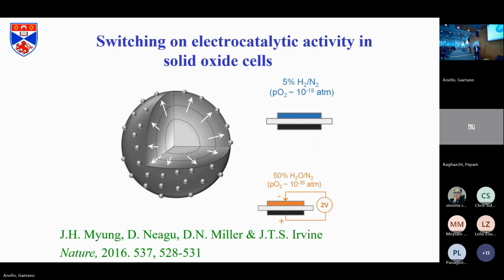If you just work out what the Nernst potential is for 2 volts, it tells you the oxygen partial pressure is 10 to the minus 35. Now, there are stray voltages, so that's not exact, but it gives you an order of magnitude. So it's much more reducing than the chemical additions.